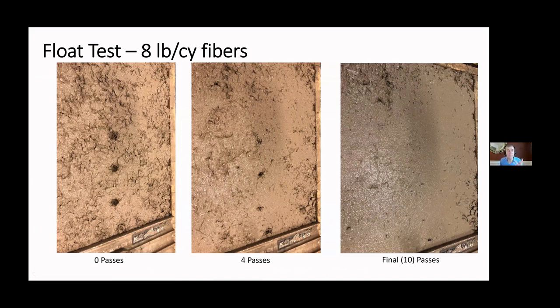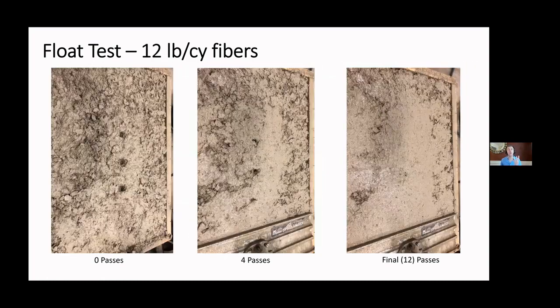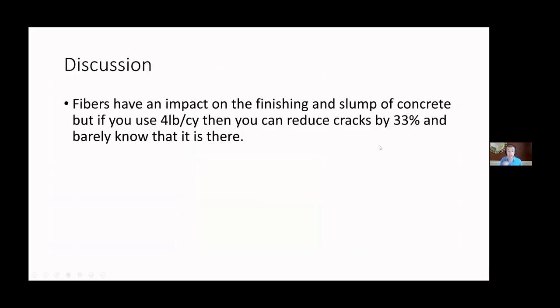We want to make it as easy as possible for our people in the field, because then we have a chance to get it adopted and get people to use it. Now here's 12 pounds per cubic yard. Look at that. At 12 passes, it still wasn't finished. It still wasn't good. That's unacceptable. So fibers have an impact on the finishing and the slump of the concrete. But if you use about 4 pounds per cubic yard, you can reduce your crack size by 33%, and you barely know it's there. You may need a little bit more water reducer to make it work out.